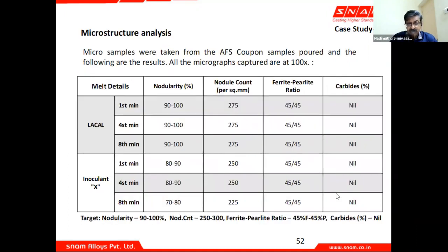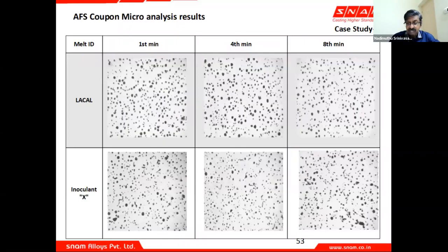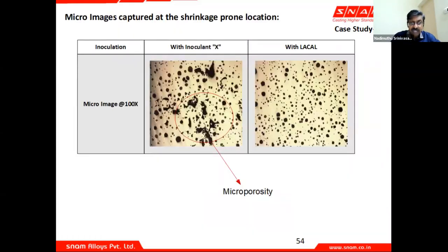And in the microstructure, in terms of X, the nodule count and the nodularity. So based on this, you can find that a better response to microporosity is addressed with lanthanum. We can see the microcoupons here, the AFS microcoupons, and you can see here the microporosities with a pure ferrosilicon based inoculant and lanthanum based inoculant.